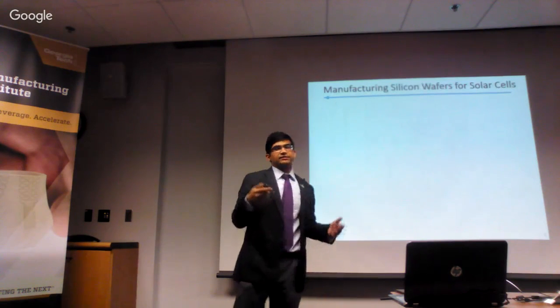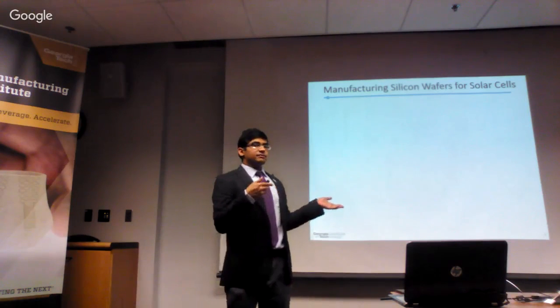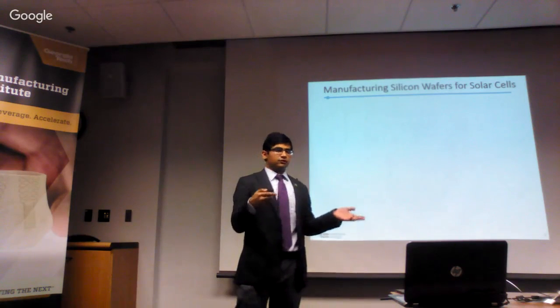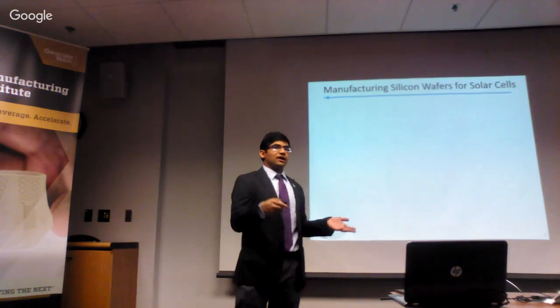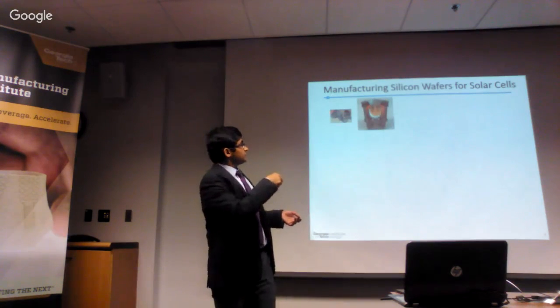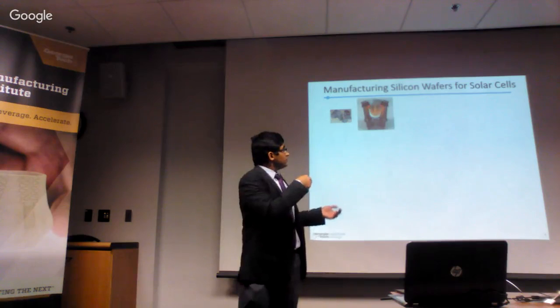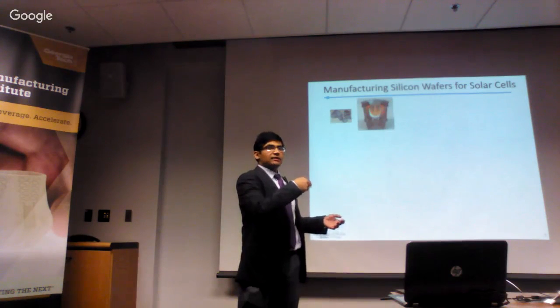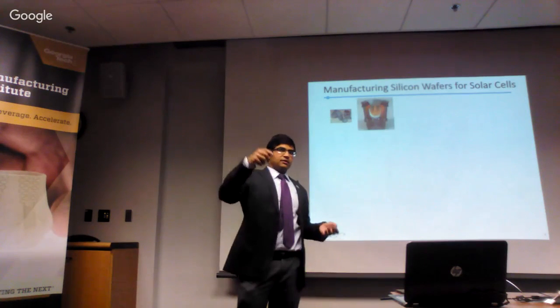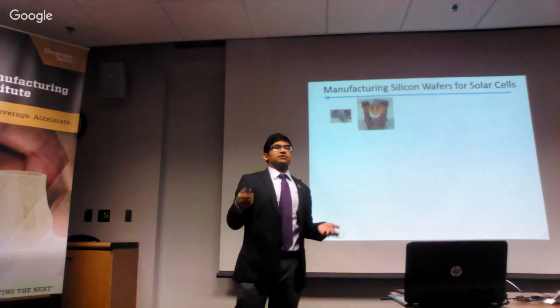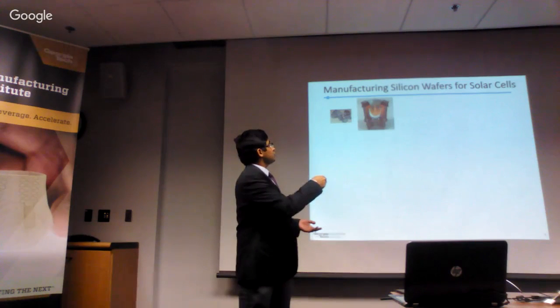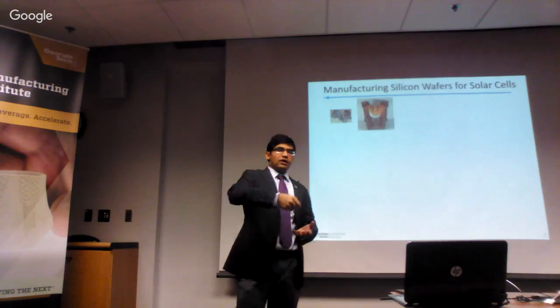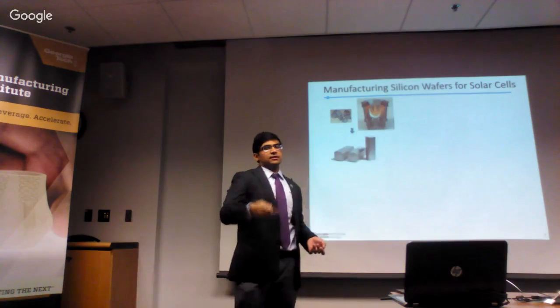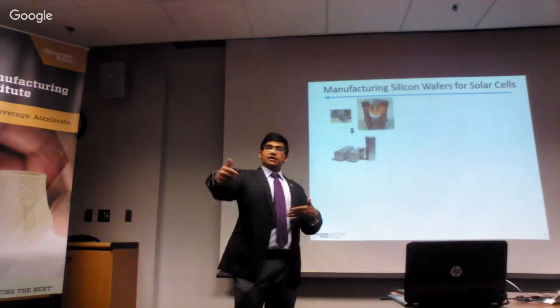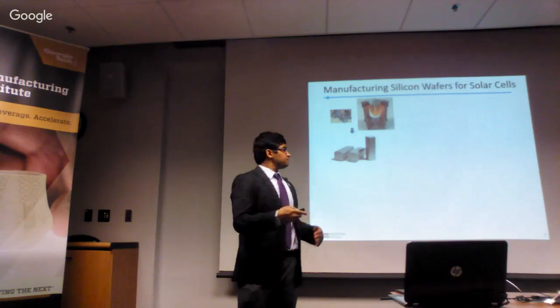Which brings us to the next slide on the manufacturing process of silicon wafers for solar cells. It all starts with silica, which is like sand, which is molten in crucibles and then pulled out of the melt by a process called Czochralski process for monocrystalline silicon, as shown here, an ingot being pulled out from the melt from a seed crystal, or they're cast into ingots for multicrystalline silicon.